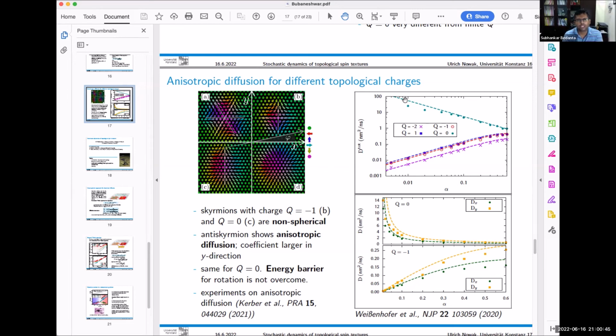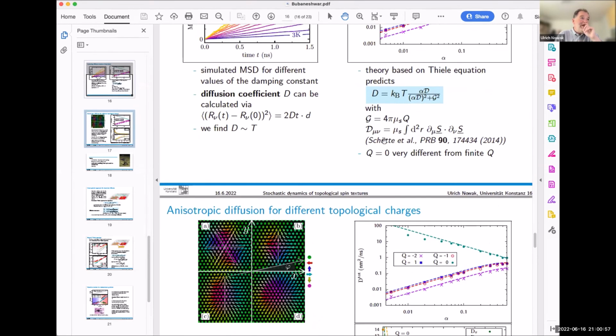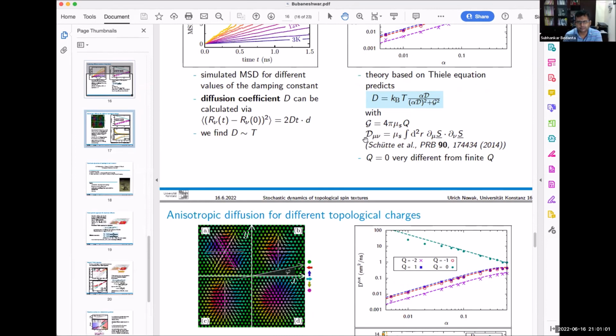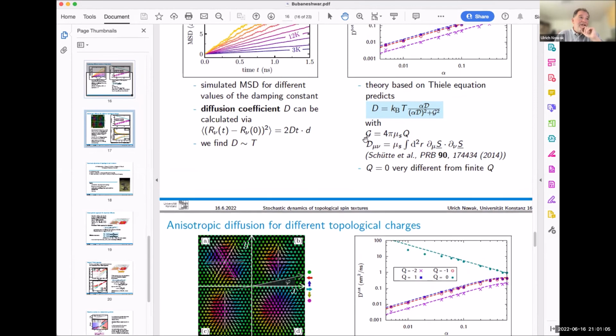Yeah, and logically thinking, if your skyrmion size is bigger, then the Brownian motion will be less, isn't it? If they are bigger, then in this formula, that means that D is larger. And if the D is larger, yeah, it depends a bit on the ratio to G. I think in very large skyrmions, this D is much larger than G, but I'm not sure that alpha D is much larger. So it's tricky. In the very large limit, the diffusion coefficient should go down with size. Yeah. But I think the bigger effect is that the larger ones will catch more defects. That's probably the bigger effect. That's also a more practical aspect. So they will be more under the pinning potential, so to say.